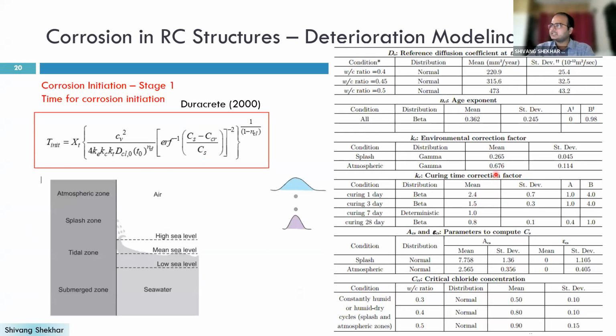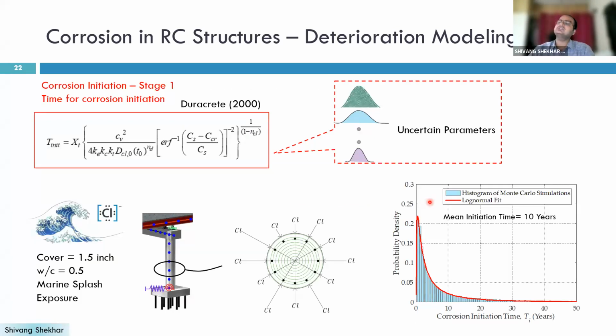Then, taking the uncertainty of these parameters, which is mentioned in this table, we do a Monte Carlo simulation. That means we generate random samples of all these parameters, and based on this we estimate the initiation time. Since we have random parameters, we get a histogram from the Monte Carlo simulation, and on that histogram we can fit a distribution. Based on the uncertainty of the parameters and considering this fixed cover depth and water cement ratio, we get a mean initiation time.